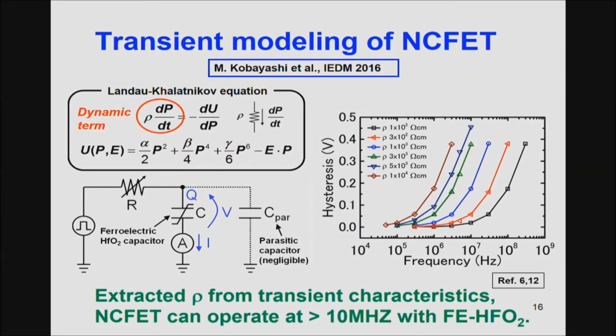I did some simulation on the operation speed of the NCFET, but the question is how real it is. I just assumed a 100 picosecond time constant, but I was wondering how real it is. So the next interest is to experimentally extract the parameter which governs the dynamics of NCFET operation. The model is usually based on the Landau-Khalatnikov equation, and here's the dynamic term, and this parameter rho is an important parameter. I fabricated a ferroelectric hafnium oxide capacitor, built a simple measurement system, analyzed the data and extracted the parameter rho. And again, I simulated transient characteristics of the NCFET. Again, the NCFET can operate faster than 10 megahertz, which is again good for IoT application.